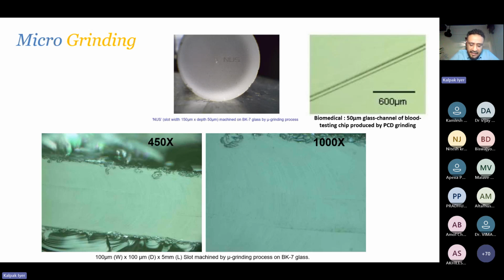Okay, so it is not really conceivable to put a glass workpiece on a machine and get on with it. You know what is going to happen? It's going to shatter. So you need to be careful about how you handle glass or other brittle materials, and you need to get a lot of the parameters right, especially the tool speed, the tool type. Here we use some kind of PCD or CBN grinding heads or some other abrasive media, and we give very light depths of cut. We have a very narrow range of the depth, and we are able to do micro grinding successfully. A lot of work on this has happened at IIT Patna. Very good work on the micro grinding on glass.